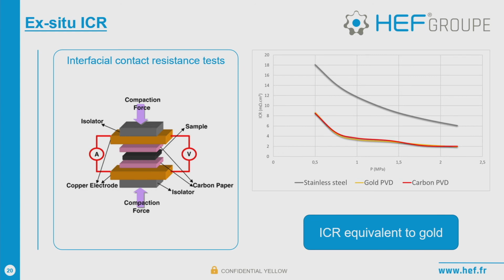The objective was to have a carbon coating equivalent to gold. So you have two things you need to secure. First thing is the interfacial contact resistance. It's the conductivity of the coating. And so you can see the red curve is equal to the yellow curve. So it means the carbon has the same conductivity as gold. So the first point is good.